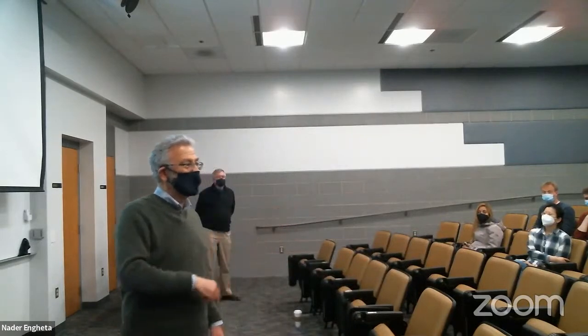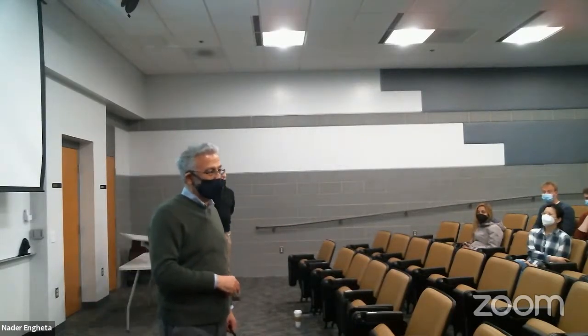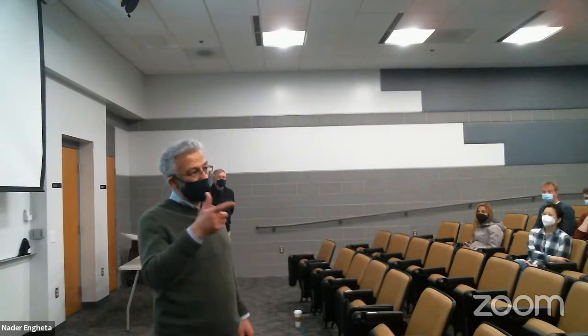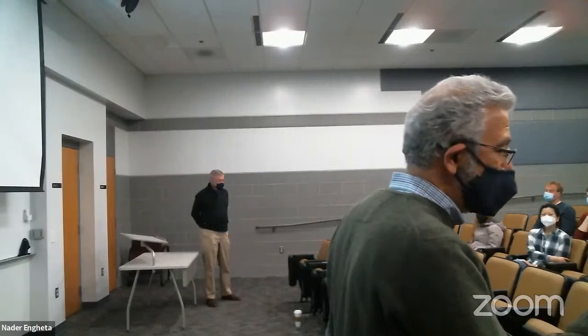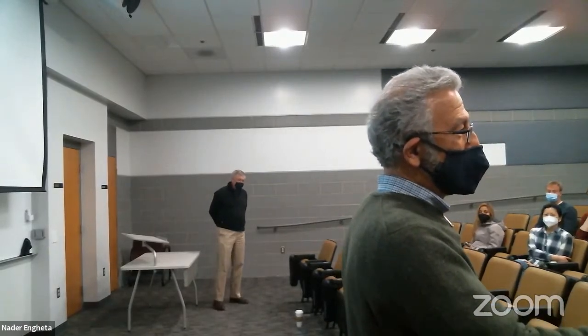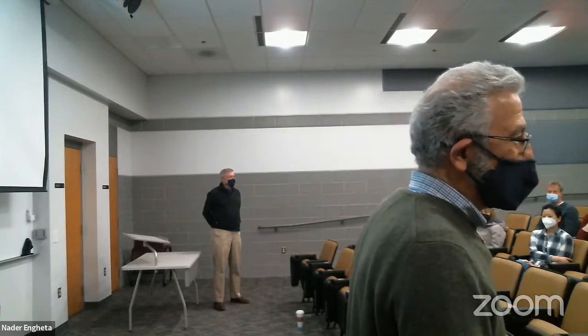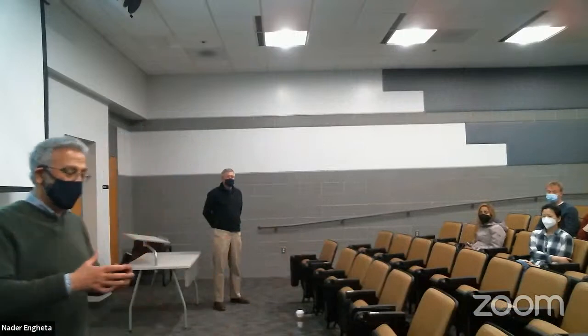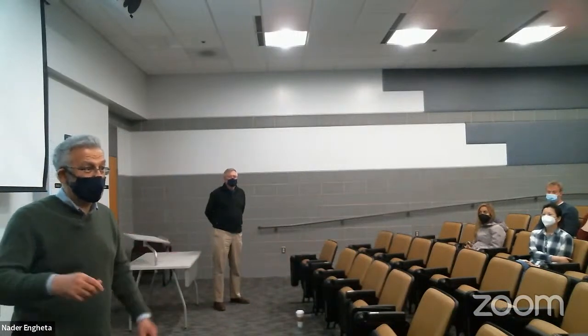And I'd be happy to talk to you later on what effect that has. I recently published a paper on that concept, which is very different from this ENZ talk I gave here. It is about what happens to the Kramers-Kronig relation in linear time-varying materials. We thoroughly studied that, and what happens is actually very interesting. The Kramers-Kronig relation is generalized, so you have double-sided frequency conversion. But yes, if you bring it close to zero and take the dispersion into account, then you can actually do the time variation.